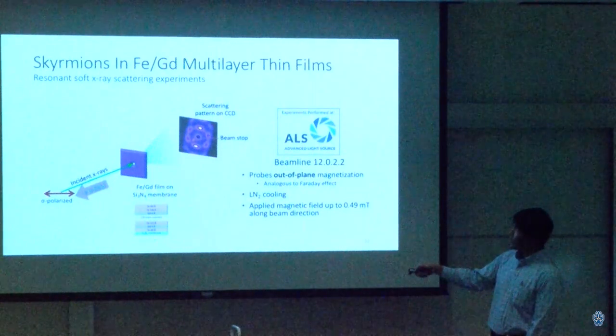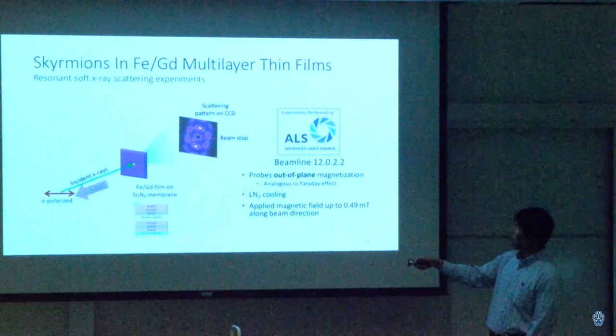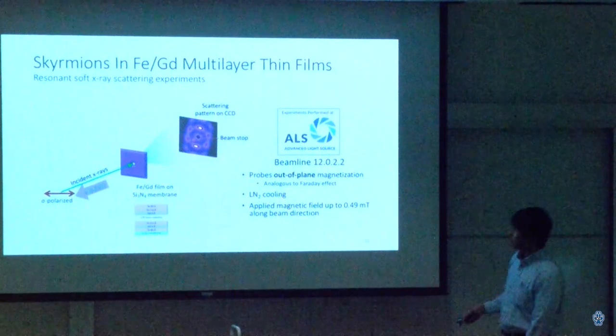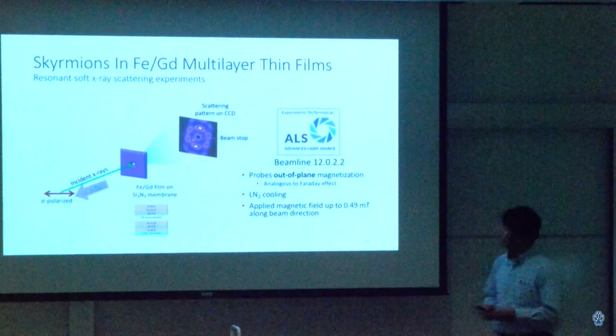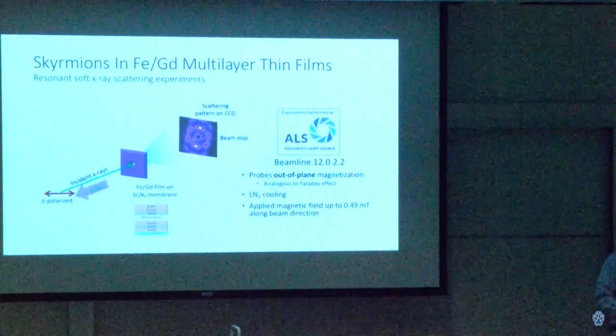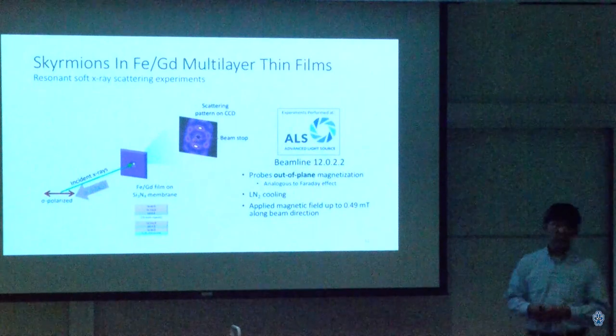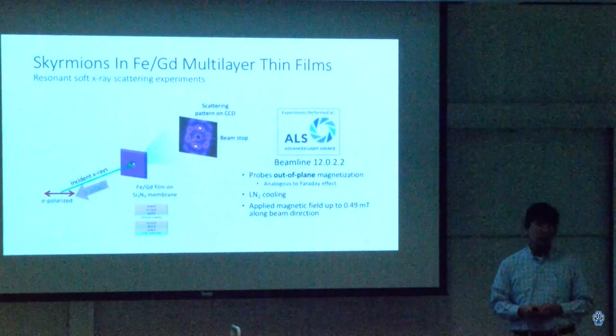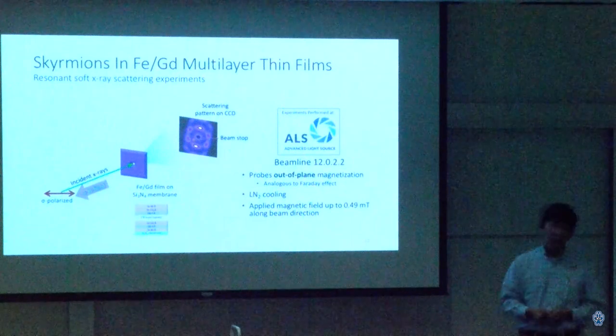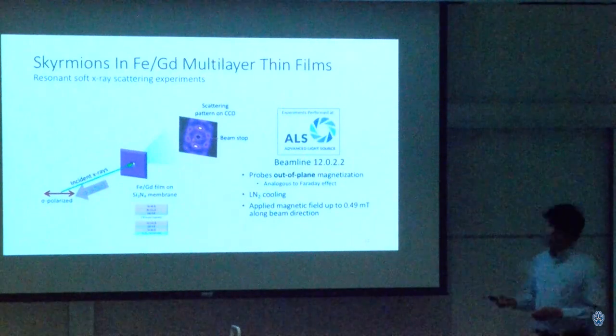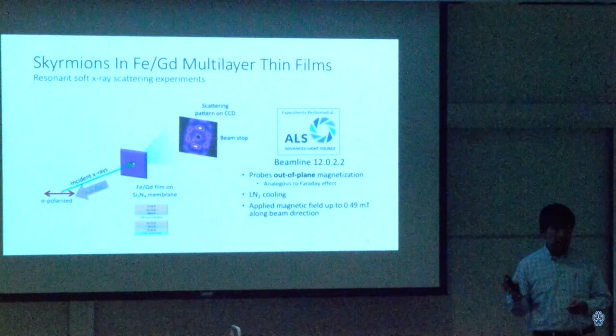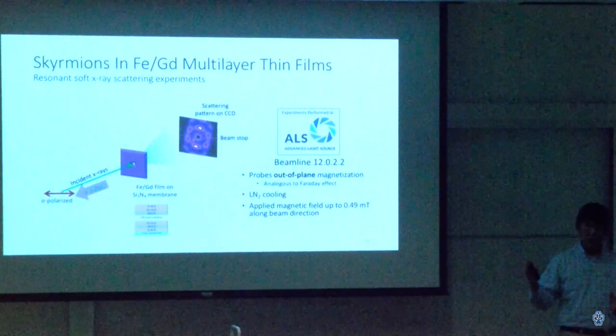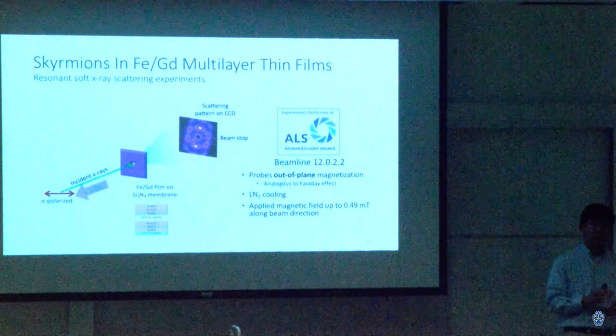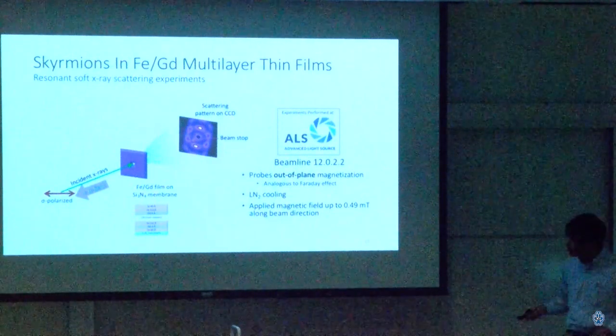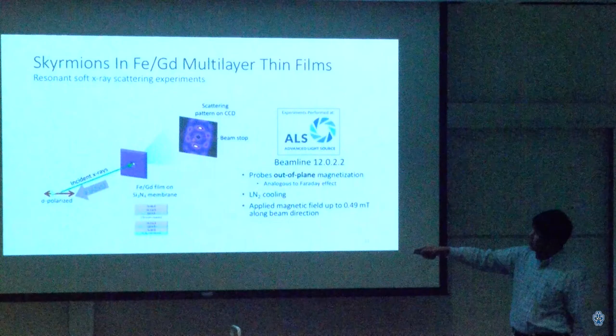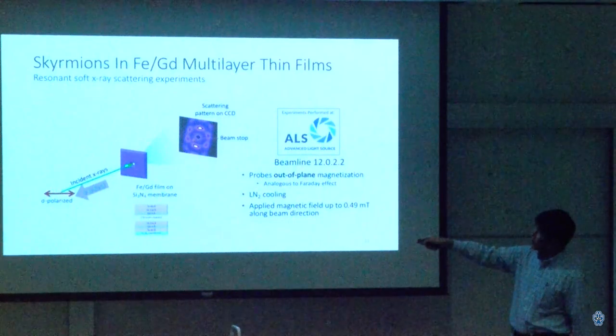So that's how they created this multi-layer sample. Sorry about that. Since I worked at the Advanced Light Source, which is a giant X-ray generating machine at Lawrence Berkeley National Laboratory, our natural inclination was to just shoot it with X-rays, which is what we did. In this case, not the X-rays you might encounter in a dental lab, but X-rays with energy 10 to 20 times lower than what you might see in a medical setting. And that's what goes from left to right. That's what this green beam represents.